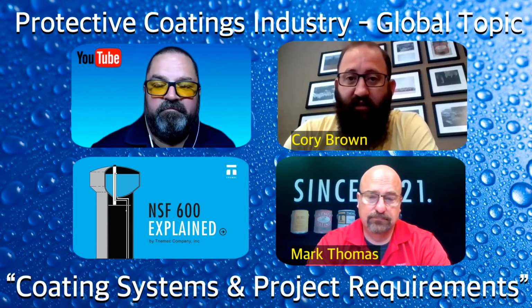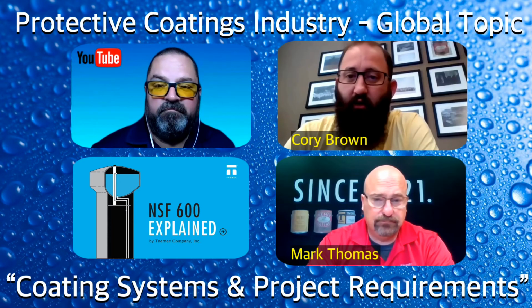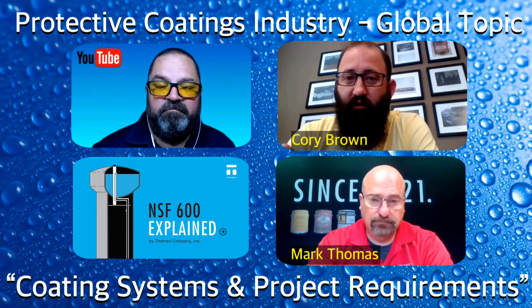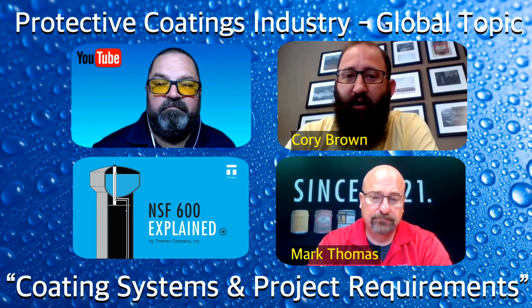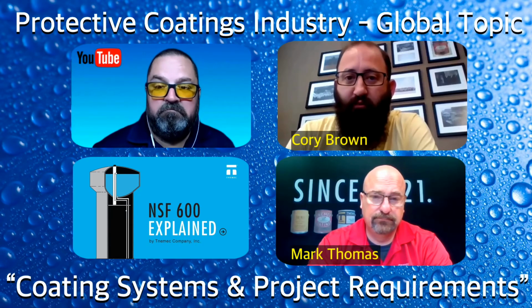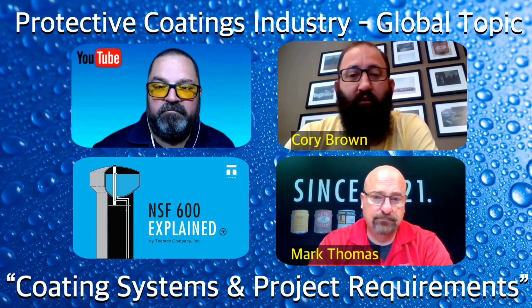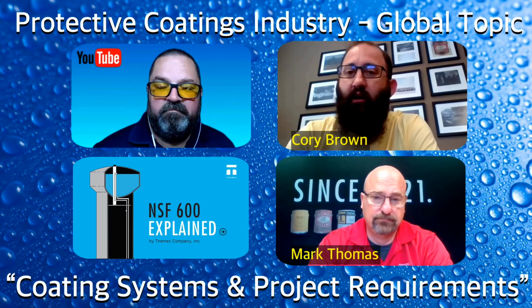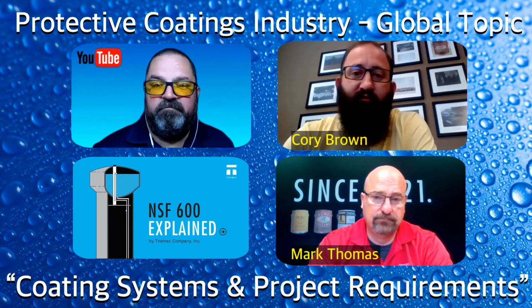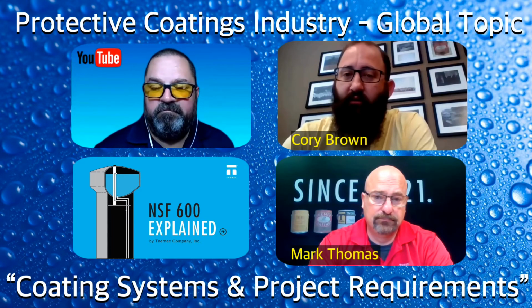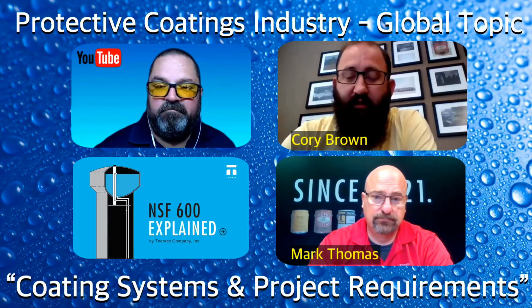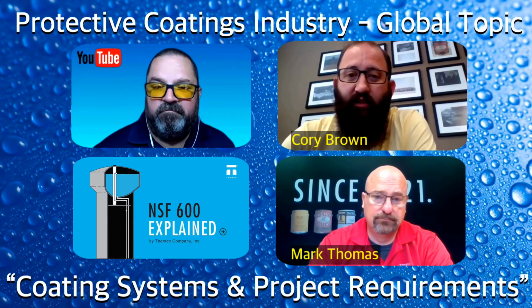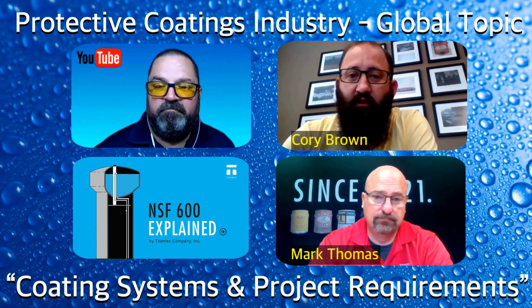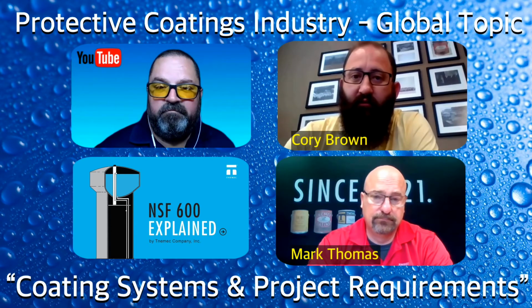And these standard test methods are always written to try to exclude as many variables as possible and make the test as repeatable and reliable as possible. Well, coating thickness is one of those variables that they try to keep a really tight rein on. So we are certified with our coatings to a certain thickness, and if field applicators exceed that thickness, then there are some conversations that have to occur about whether that lining is still compliant or not.